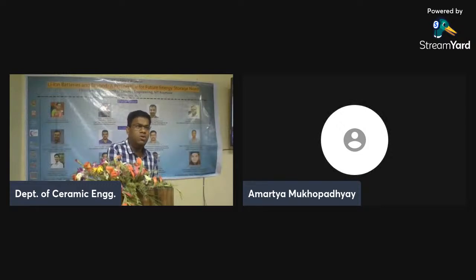Thank you. I have specific questions regarding your zero manganese, 0.5 titanium, water and air stable sample. You mentioned it's very electrochemically stable, giving a decent capacity and stable up to 100 cycles. I was wondering, when you are trying to extract sodium, because this is an O3 type layered oxide, what is actually happening in the structure? Because all these magnesium, copper are electroinactive, even including titanium. So if your sodium comes out, how is the structure being retained? Because there is no redox couple, it appears.